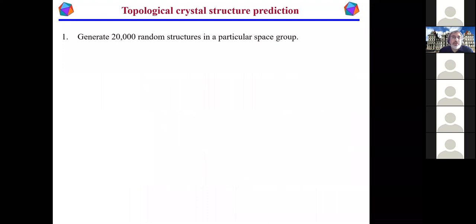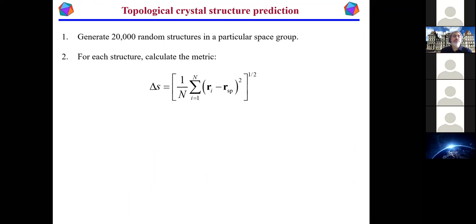Okay, so the next step is to exploit this topological order parameter business to try to come up with a way to predict an actual crystal structure. So again, let's start with some random structures. So you take a space group, you generate some tens of thousands of random structures, and then you would formulate a kind of distance metric. So you take your special positions, right, that you've predicted from your order parameters. You take the atoms that are in your unit cell, all right? So the number of atoms is n.